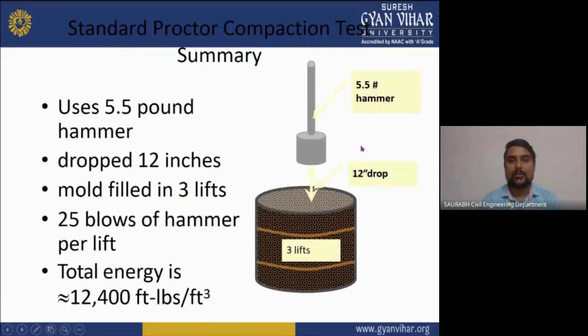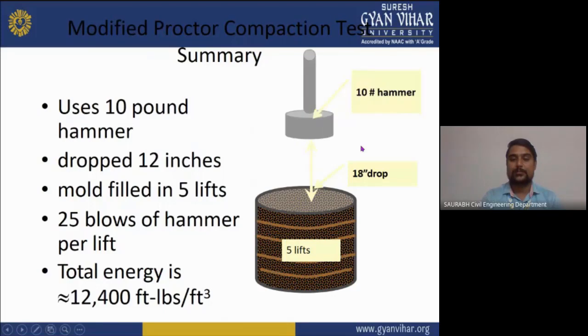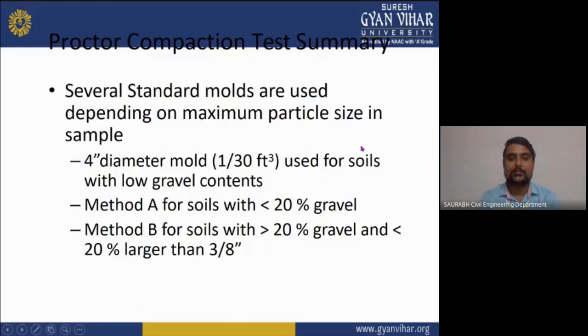Now we will see the summary of the standard Proctor test. As you can see, that is your hammer, which has a weight of 5.5 pounds, and the drop distance is given here as 12 inches. It uses a 5.5 pound hammer, 12-inch drop, mold filled in three lifts, 25 blows of the hammer per lift. The total energy consumed here is 12,400 foot-pounds per cubic foot. And here, you can see it is the same thing.